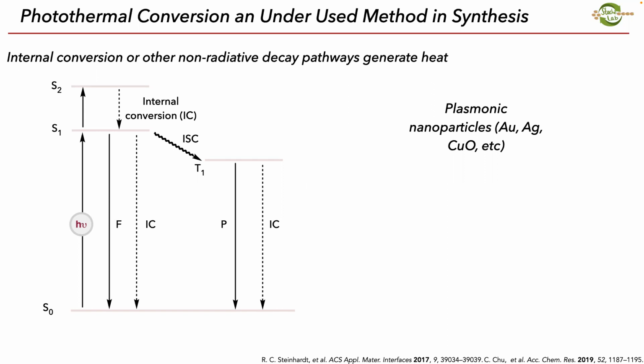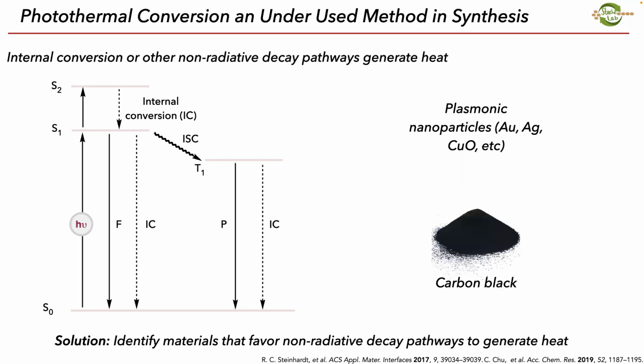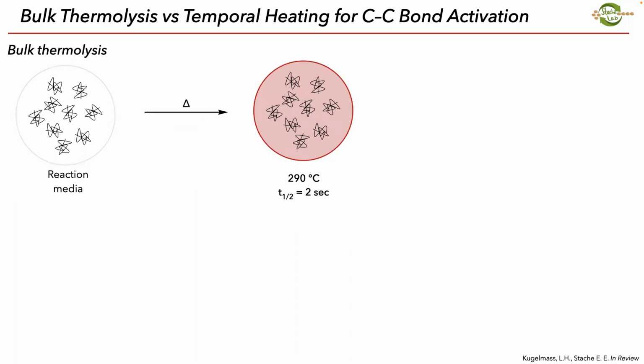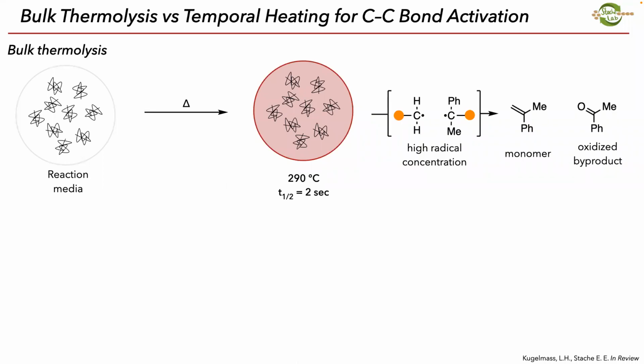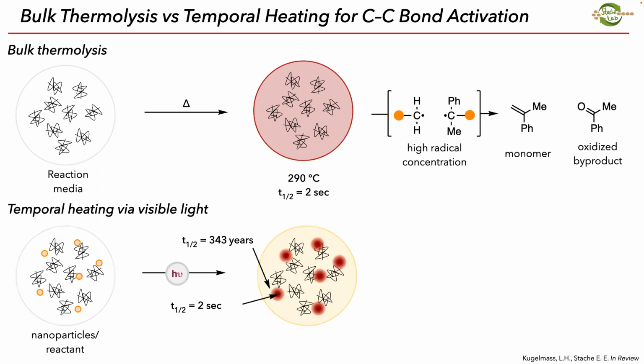And so there are a lot of inorganic materials that will do this: plasmonic nanoparticles like gold and silver, copper oxide, and carbon black, which is an oil petroleum feedstock and very cheap. And so what we sought to do is identify materials that will undergo this non-radiative decay to generate thermal gradients so that we can generate radicals. So comparing bulk thermolysis, where we heat up the entire solution to 290, so there's a very short half-life of these radicals, we get a high radical concentration, we get oxidized byproducts, or using this idea of temporal heating, where we have these nanoparticles which will absorb visible light, relax back down non-radiatively, and generate thermal gradients such that only the polymers or the carbon-carbon bonds that are in proximity to those nanoparticles will cleave and generate radicals.